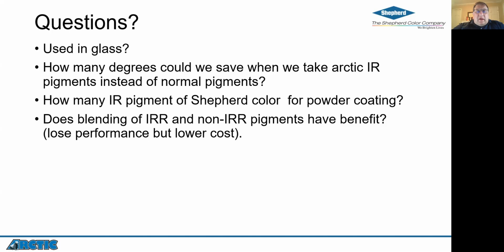Does the blending of infrared reflective pigments and non-infrared reflective pigments have a benefit, like a lesser performance but lower cost? What we found definitely, and I mentioned it earlier with the contamination, is that the inclusion of even a small amount of non-infrared reflecting pigments greatly degrades the overall reflectivity of the system. So if you take carbon black and add even a tenth of a percent on pigment basis to an infrared reflecting black, you're going to reduce the reflectivity by over half. It doesn't take very much, especially of a very strong pigment like carbon black, to reduce the reflectivity.